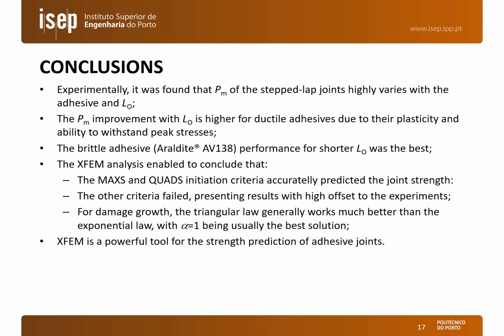Regarding the conclusions, experimentally, we saw that the maximum load of the step joints highly varies with the geometry and also with the adhesive chosen. We have a higher improvement of the strength with the overlap length for ductile adhesives due to their capability to undergo plasticization, which does not occur for the brittle adhesives. And regarding the XFEM analysis, we saw that this is actually a powerful tool for the strength prediction of adhesive joints if we correctly choose the criteria for both damage initiation and damage propagation.